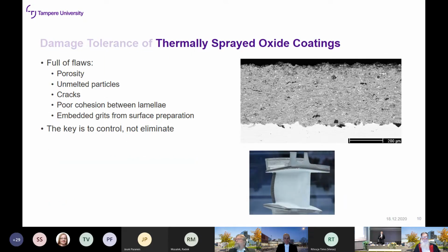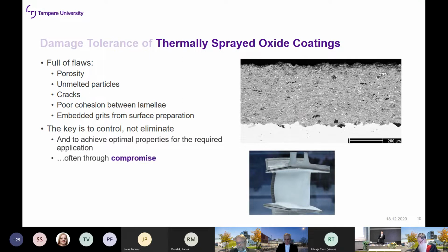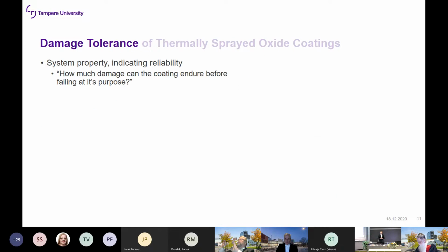And thermally sprayed oxide coatings have a ton of flaws. The process is stochastic. There are uncontrollable factors or difficult to control factors which lead to porosity, unmelted particles, cracks, etc. And it's very difficult to eliminate these totally. So most often we try to find the best balance and control them as well as we can, and to find the optimal properties, which means compromise. Some property goes up, some goes down. Most often we haven't found the perfect solution to make everything better.